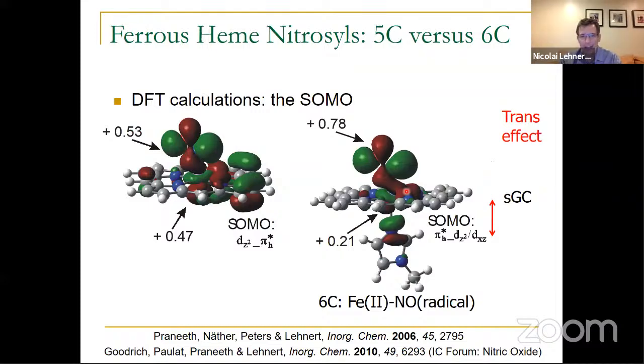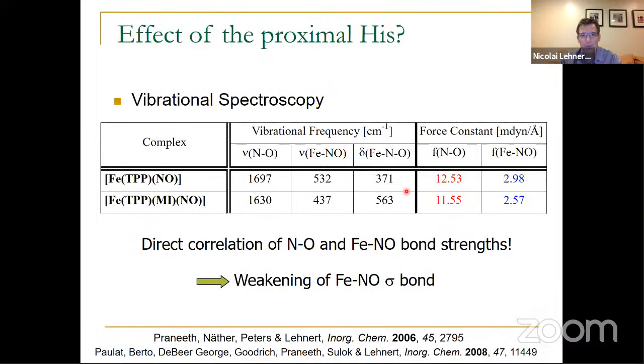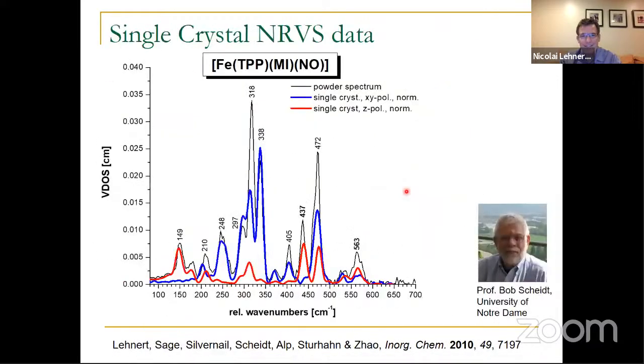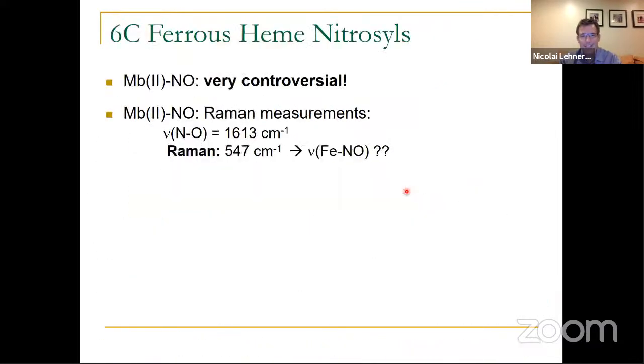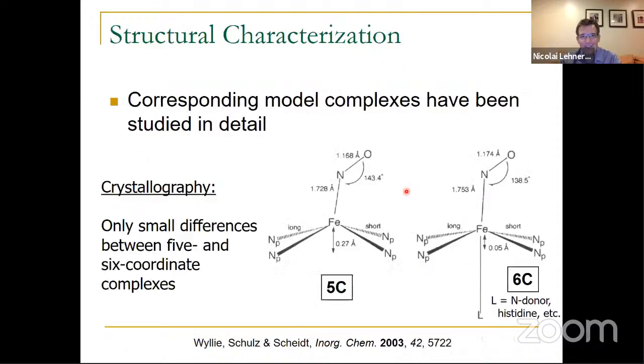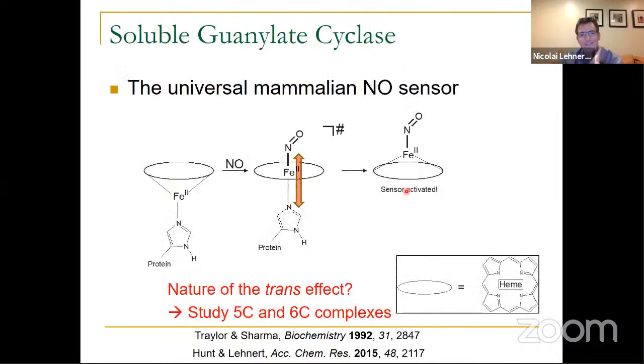So if we go back then to the slides, I guess I should have, yeah, here it is. The trans effect that breaks this bond, we can call a sigma trans effect, and it's mediated by donation of NO into the dz square orbital of the heme, which weakens the iron imidazole bond. It breaks, and that leads to the formation of the 5-coordinate complex, and that activates soluble guanylate cyclase.